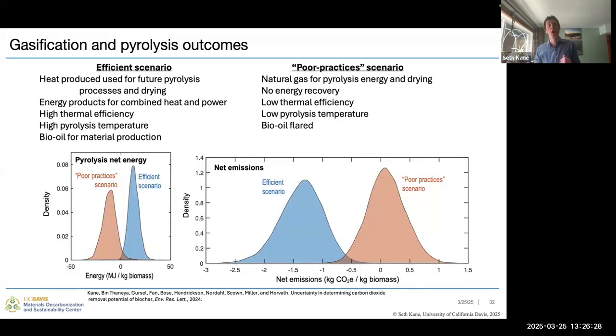And so these figures are showing an uncertainty assessment of those two scenarios. And just to give an idea, even with fairly high uncertainty considered, in that inefficient poor practices scenario, across basically the entire distribution, we would have to be putting energy in, whereas in an efficient scenario, we get energy out across the entire distribution. And similarly, for the net emissions, we are storing carbon across basically the entire distribution for an efficient scenario, whereas it's very uncertain whether we emit or store carbon in that inefficient scenario.